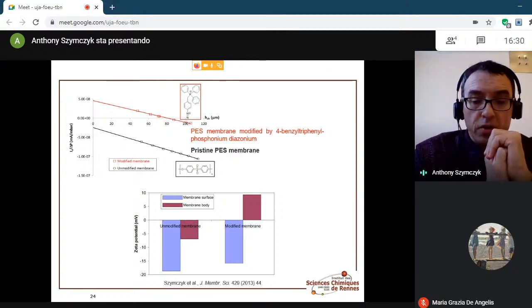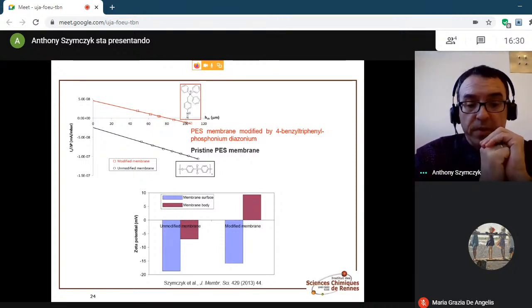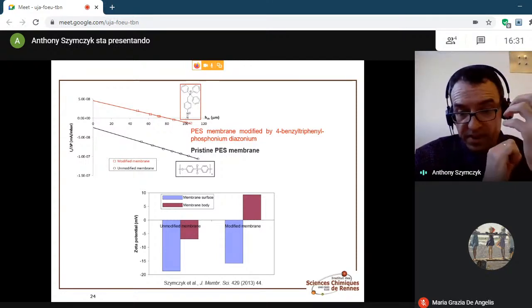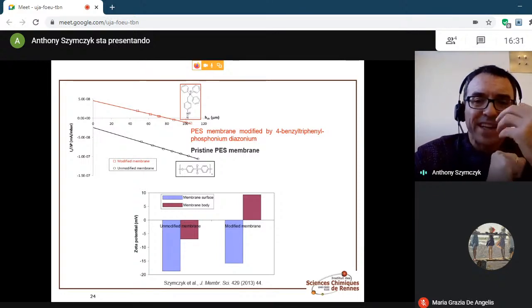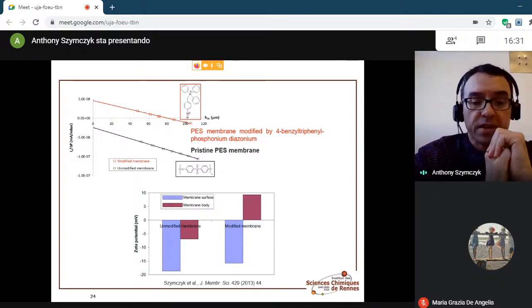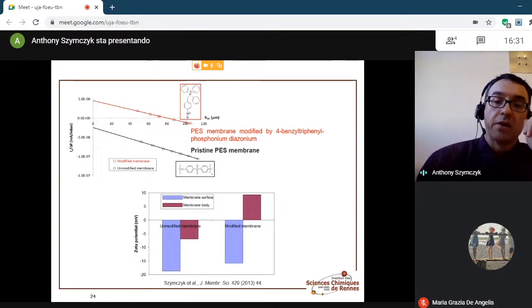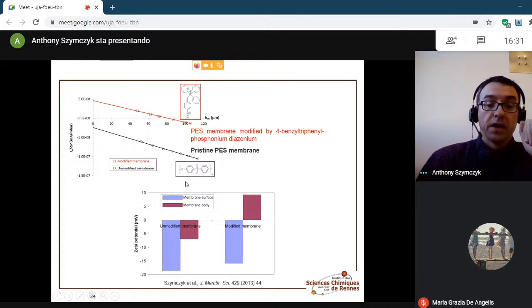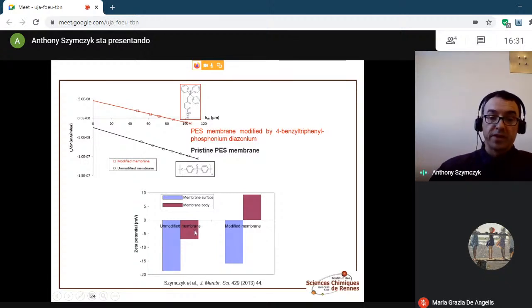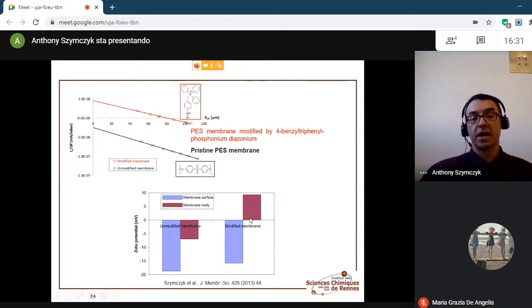The next slide shows the results of this procedure, combining streaming current and electrical conductance measurements for different distances between samples of negatively charged polyether sulfone membranes functionalized by a species carrying a positively charged phosphonium group. It was thus possible to prove the presence of the positive phosphonium groups inside the membrane pores through the change in sign of the zeta potential of the membrane matrix before and after modification.